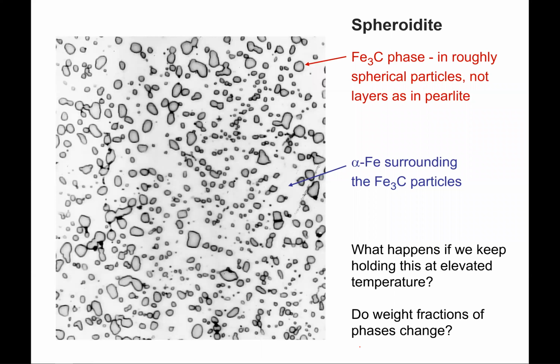So if we keep holding, maybe this is 24 hours, 48 hours, maybe 3 days, depending on the temperature, we will eventually break that pearlite up completely, and we end up with these spherical particles. I know these aren't perfectly spheres, but we refer to them as spherical particles. And so this is referred to as spheroidite.